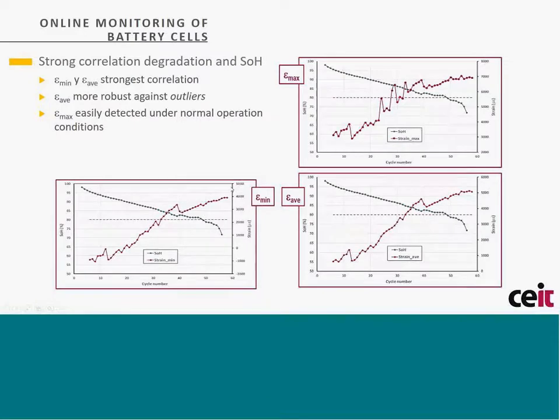And also there is a strong correlation between the degradation of the signals of the degradation sensor and the state of health of the battery. So you can see here that for, I think these are 58 different charging and discharging cycles, the values that the sensor provides have a very strong negative correlation with the state of health of the battery. So we can use the different values we get from sensors, that's maximum, minimum, or average strain values. We think that the maximum is easily detected under normal operation conditions, but we can also use the minimum and maximum and average strain measurements.